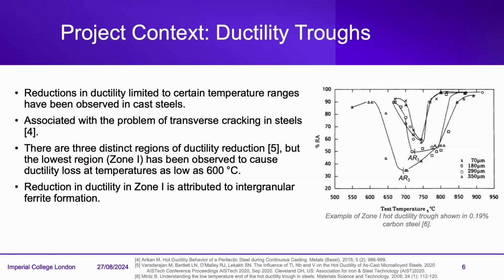Another thing to take into account is the appearance of ductility troughs, which have been known to occur in certain cast steels. These are characterized by a reduction in ductility in a temperature range. There are multiple zones for this, but the one probably of most concern is in the lower temperature range, because this can be as low as 600 degrees. These can be attributed to ferrite formation upon cooling, which then preferentially deforms and forms voids, which then coalesce and cause intergranular cracking, but it can also be due to grain boundary sliding.